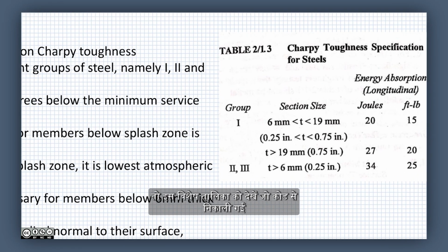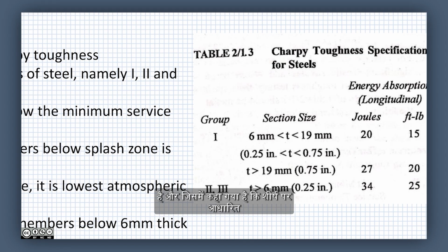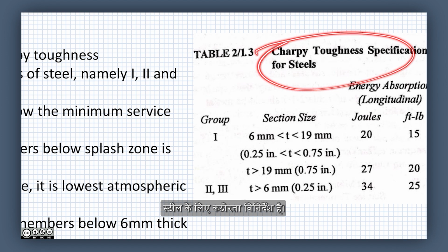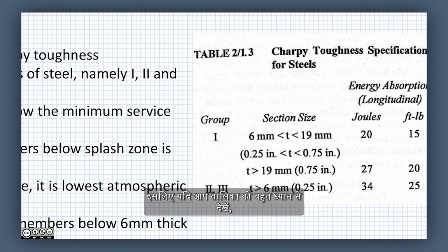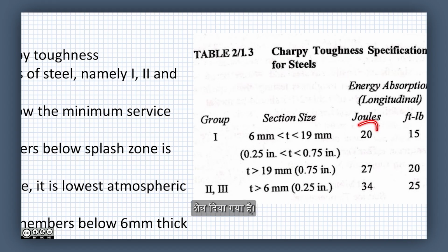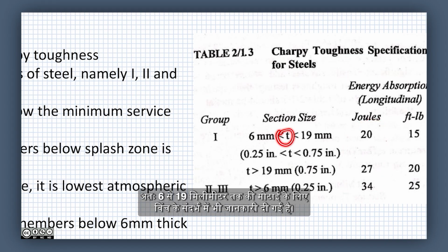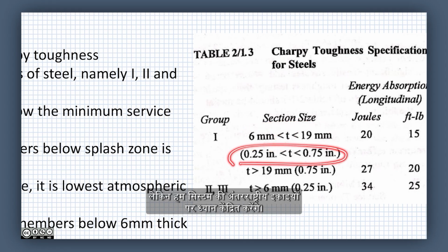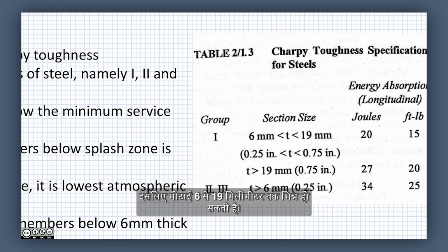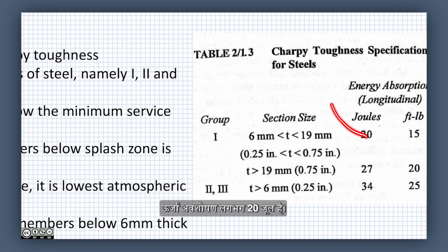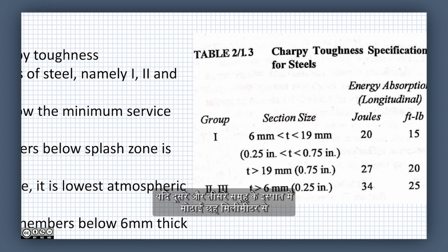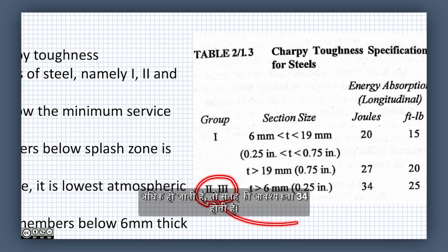So, look at this particular table, which is extracted from the code, saying that based on Charpy's toughness specification for steel, steel is grouped as 1, 2 and 3. If you look at the table very carefully, the energy absorption in the longitudinal direction in joules is given. For thickness varying from 6 to 19 millimeter, in inches also is given, but we will focus on SI units. In terms of thickness varying from 6 to 19 millimeter, the energy absorption required by Charpy's test is about 20 joules. If the thickness exceeds 19 millimeter, then the Charpy's demand is 27. If the thickness exceeds 6 millimeter in group 3 steel, then the Charpy's demand is 34.